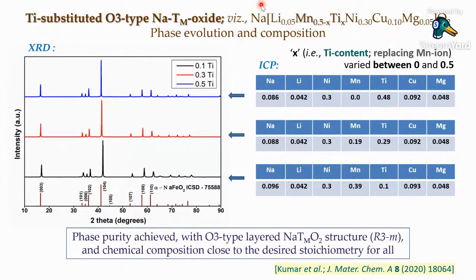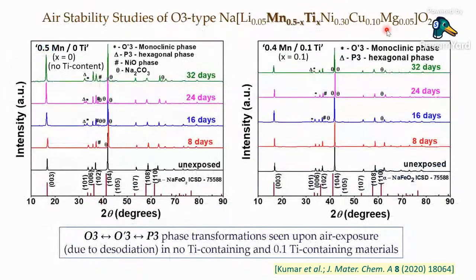Now, with all these substitutions in the transition metal layer, we could obtain phase pure O3 type structure, and we systematically varied the manganese and the titanium content. One composition had 0.5 manganese, 0 titanium. The other extreme had 0.5 titanium, 0 manganese, and there was an intermediate composition with say 0.3 titanium and 0.2 manganese. So in a stepwise manner we replaced manganese with titanium to see what happens. There are logics behind that, but I will run out of time, so I won't discuss all the logics today.